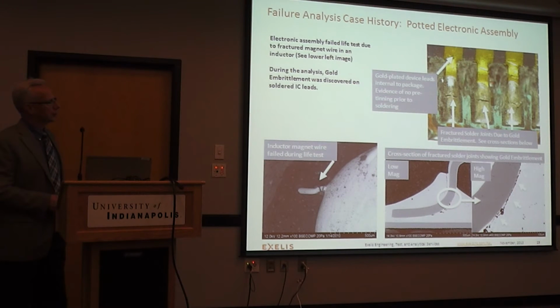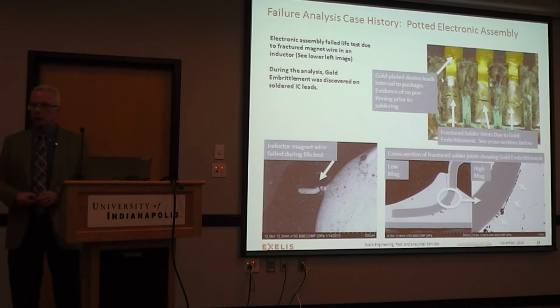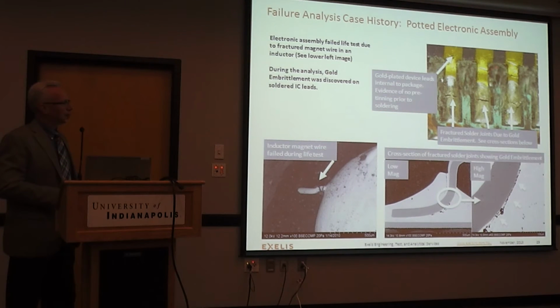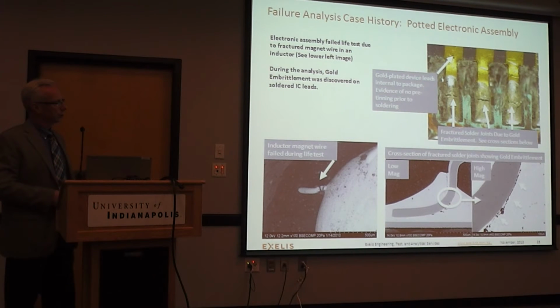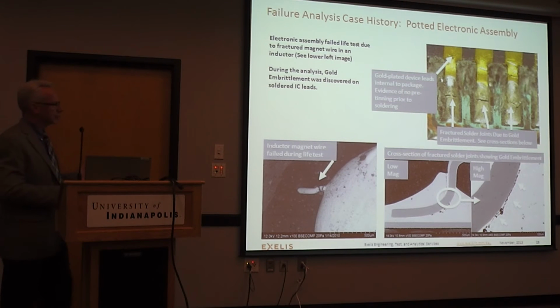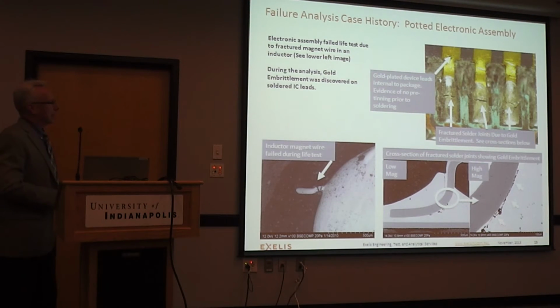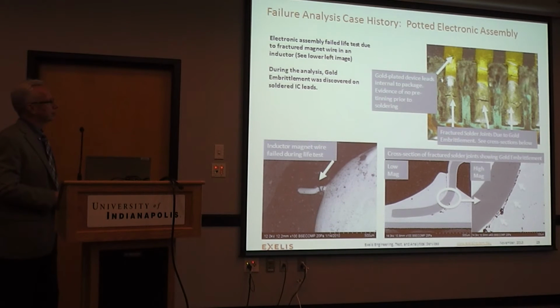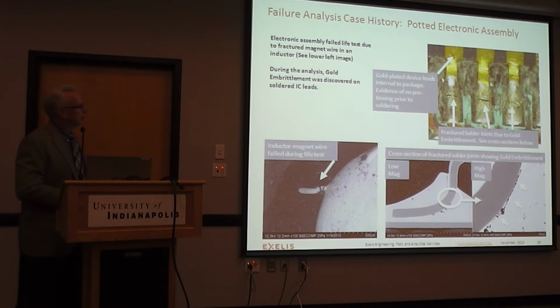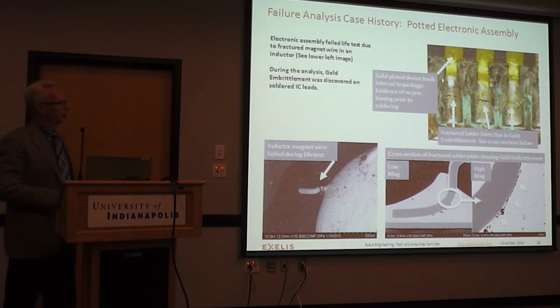This is a solder joint, and this is a gold-plated lead going up to an integrated circuit. So the manufacturer of the integrated circuit had a gold-plated finish on his leads. And the manufacturer of the potted assembly soldered that component to the circuit board. And we saw fractures in the solder joint. So these horizontal lines are fractures within the solder joint, and that was a real concern. Now, as I allude to in this text box, we saw no evidence of pre-tinning prior to soldering.